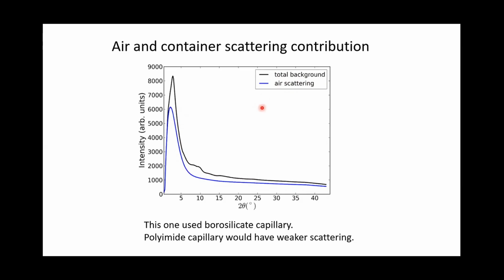For example, at APS, their 11-ID-C actually has a very long working distance, meaning that their X-ray has to travel a long distance to reach the sample, generating a lot of air scattering along the path. So they actually have a project to shorten this path so that you can minimize the contribution from air scattering. And also you want to minimize your contribution from the container, right?